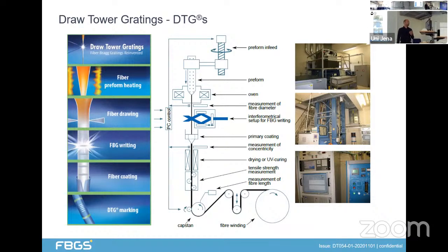After the inscription, the fiber is moved to the next position where the coating is applied on the fiber. That means with this technology, we are capable of writing the grating before the primary coating is applied. That gives the advantage that no stripping of the coating is required to write any grating, as this is done in the process before. After the coating is applied, it is cured. Then the grating position is marked, and with this highly automated process, it is possible to write in one fiber piece several hundred, even up to several hundred thousand gratings.